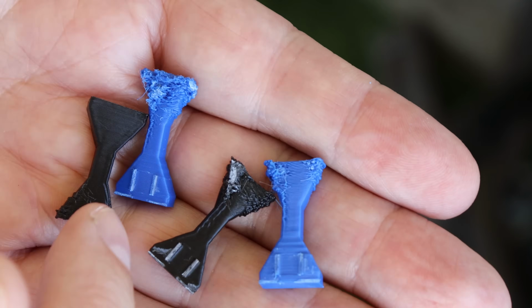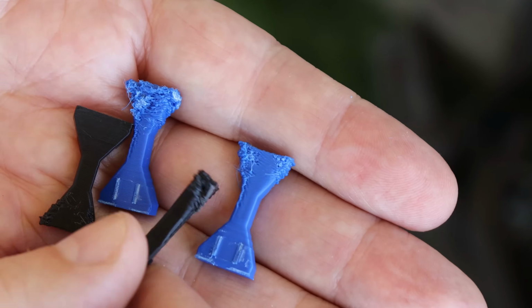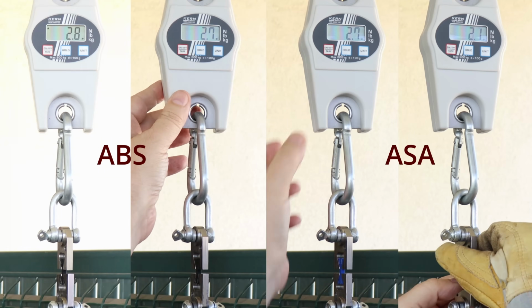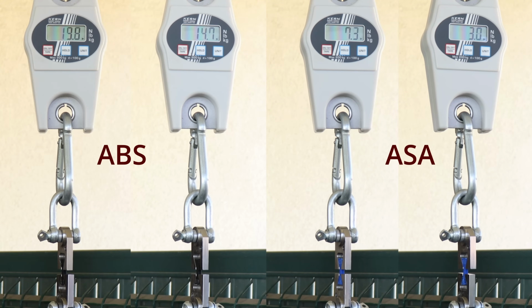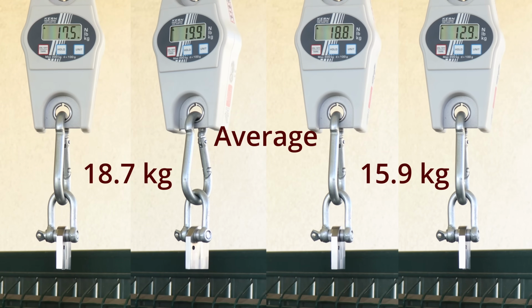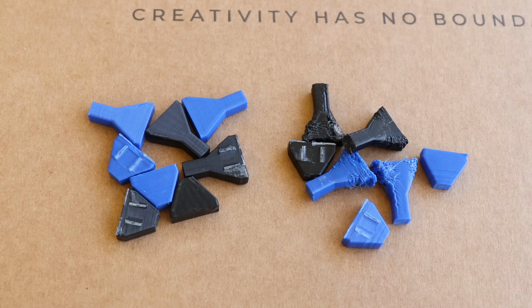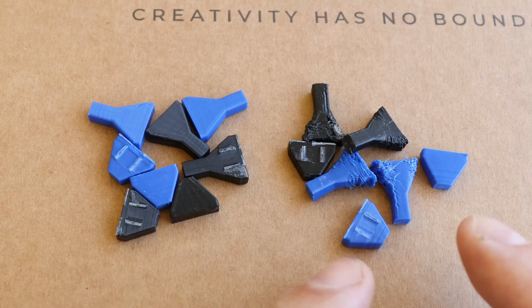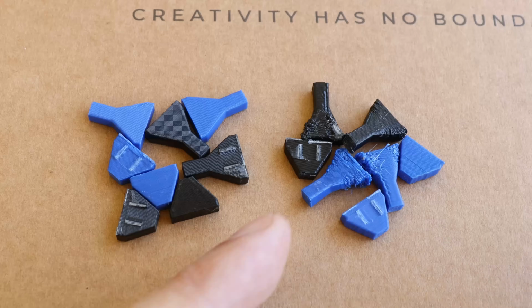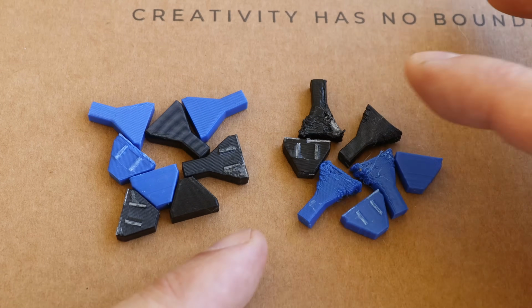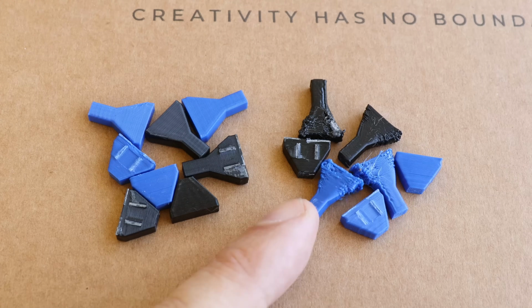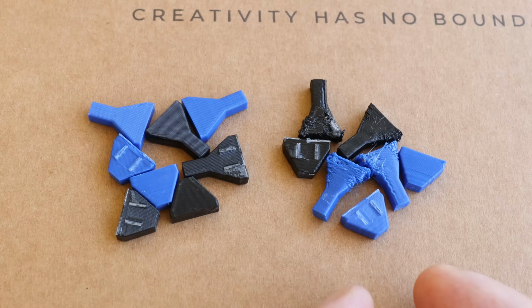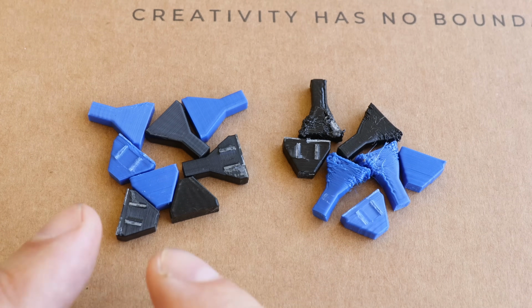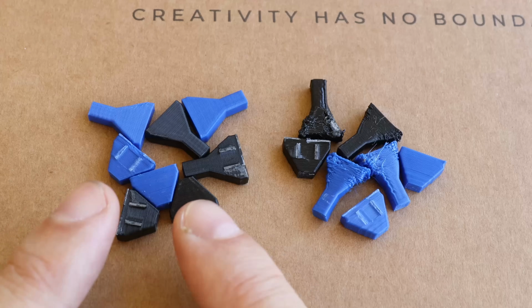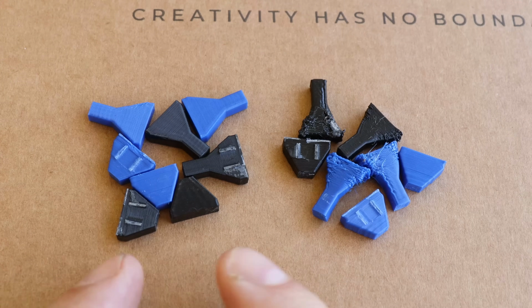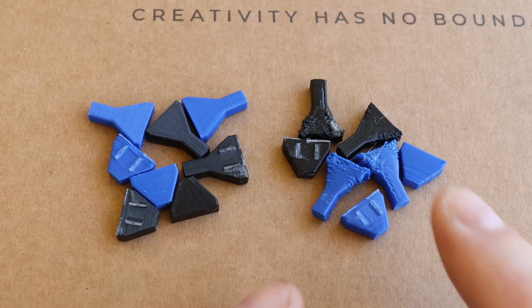Just for curiosity, layer adhesion with these test objects where the part cooling was not enough. Layer adhesion test with very low part cooling. I don't really know how to explain this. I was quite sure that this will have better layer adhesion. Maybe there is some anomaly in the cross section, or maybe they were under some angle in the holder. But definitely it is good to know that a proper part cooling results not only in nicer parts, but proper layer adhesion. It could be better, but definitely it is better than this.